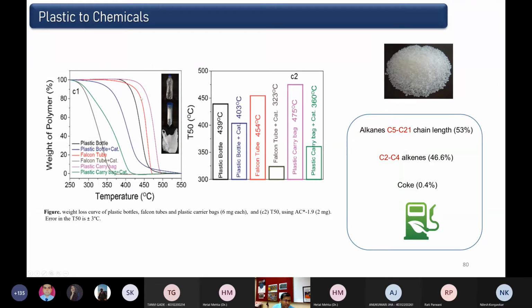This one is around 450. The plastic carry bag needs around 450 degrees Celsius, but using our catalyst, it needed around 350 degrees Celsius, 100 degrees less, right? So that was the improvement.